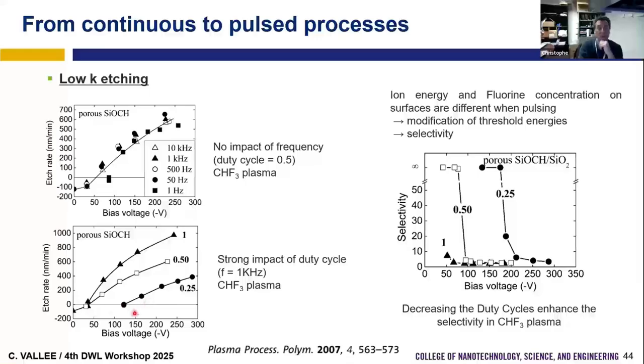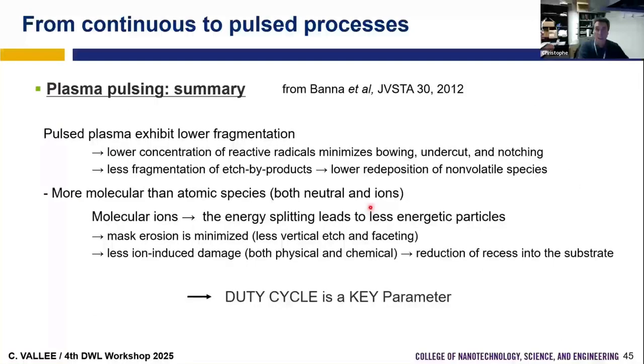So if you modify the threshold voltage, now if you want to have a selective process between low-K and silicon dioxide, you can modify your selectivity by pulsing, and you can see that you may have a huge modification of selectivity and go by pulsing to sort of infinite selectivity, in this example, with a CHF3 plasma.